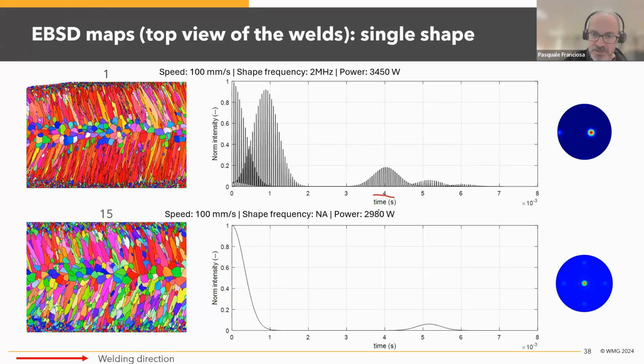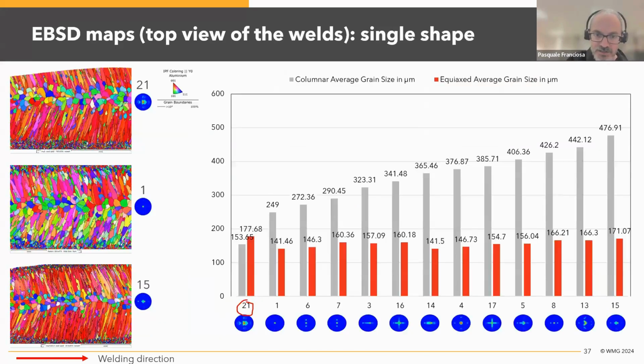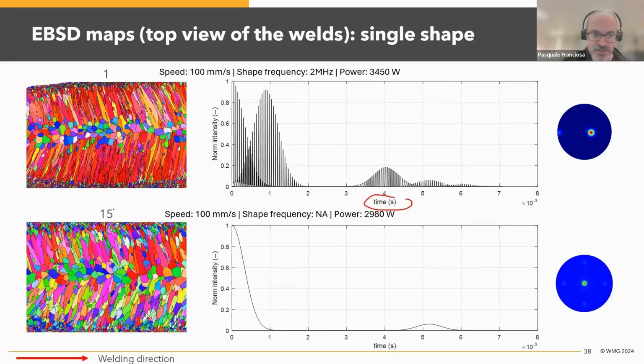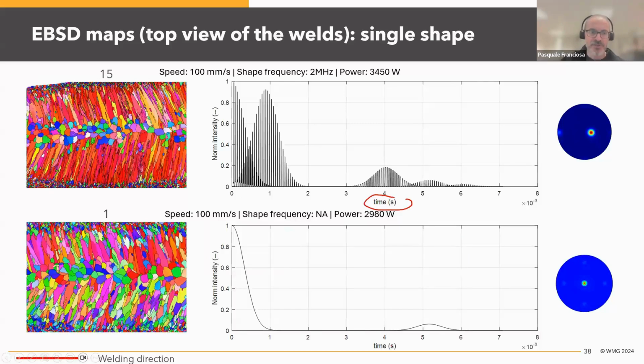So again, by plotting interaction time for those two cases, case 1 and case 15, I think the numbers are, it's the other way around, apologies. So this should be 1 and this should be 15. Right, so by plotting the interaction time against the intensity distribution monitored at the same point within the weld, you can see how the intensity distribution is going up and down, and because of that thermal cycling, we see the response in the EBSD map in the end.